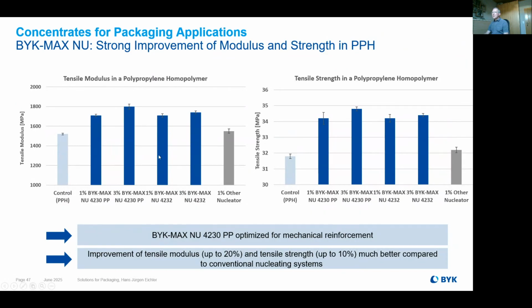If we check now mechanical properties, you see now the advantage of the 4230. This is just here shown in tensile modulus and in tensile strength. You see that the values from these products are on a slightly higher value compared to the 4232, which is doing a quite good job. But as I said, 4230 is optimizing mechanical properties. On the gray side, you see other nucleators which are also doing a good job. But in case of that, compared to our material, we are more efficient, also with lower amounts. And just as a summary, in case of the tensile modulus, we can really increase it up by 20%, and tensile strength is increased up to 10% with both materials.